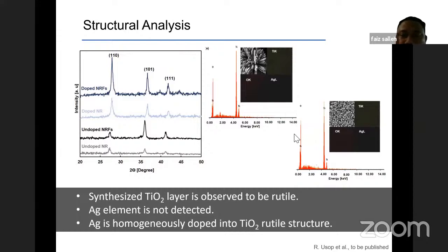So that's why we consider that it's quite difficult to see the mapping of argentum or the silver inside this elemental mapping. So we can conclude from this XRD and EDX result that the synthesized TiO2 layer is observed to be rutile. Silver element is not detected, and we can also consider that the silver is homogeneously doped into that TiO2 rutile structure.